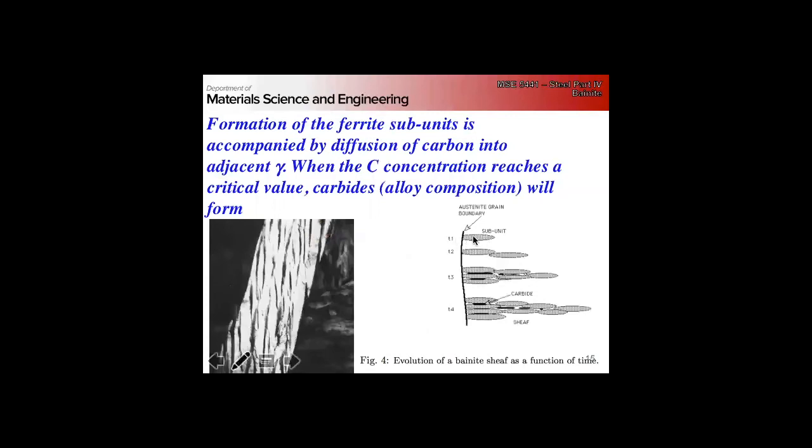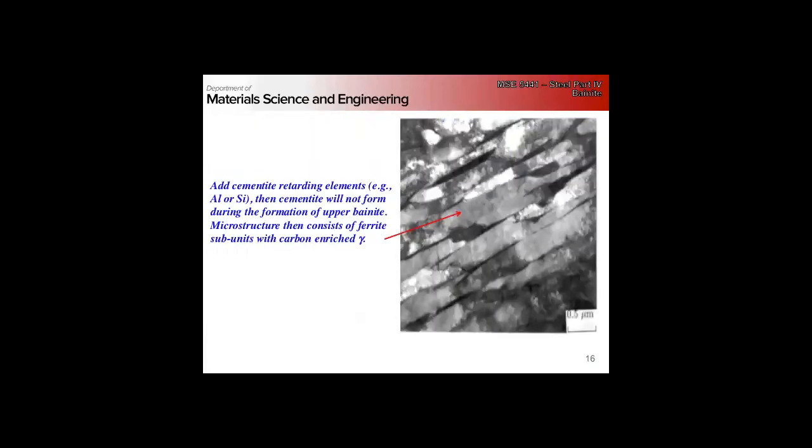The mechanism: we grow a subunit, and that subunit grows very fast. Then we diffuse the carbon out, and the carbide grows between the subunits. Because the subunit grows very fast, but then we have the overlapping, the growth of the overall sheaf is much slower than the growth of the individual subunits. The subunits lengthen quickly, but the sheaf lengthens more slowly.